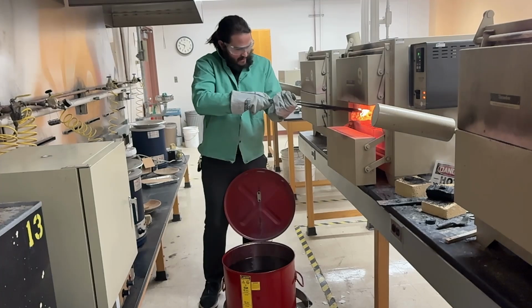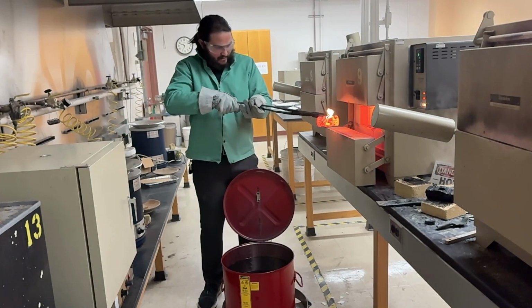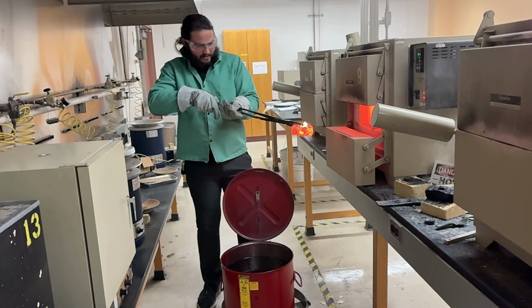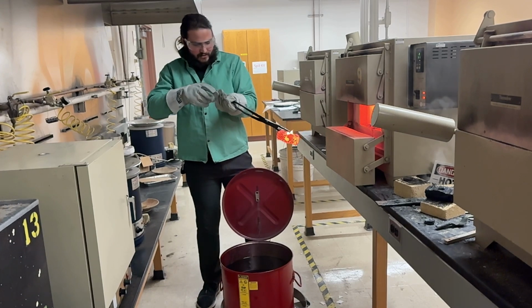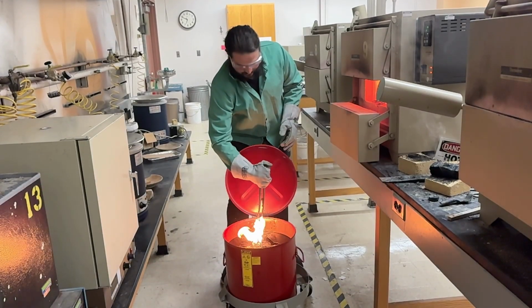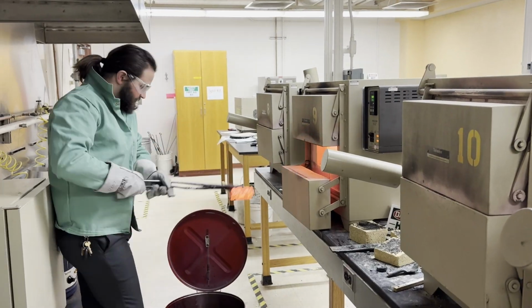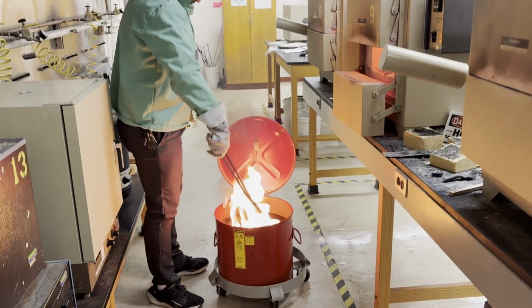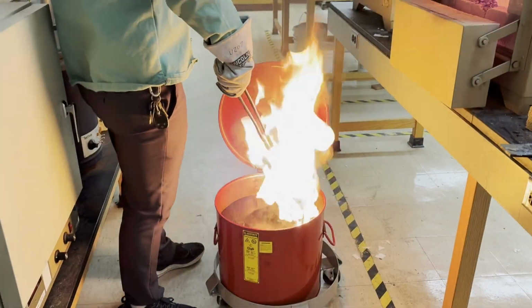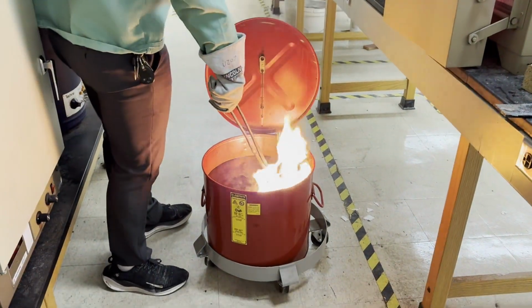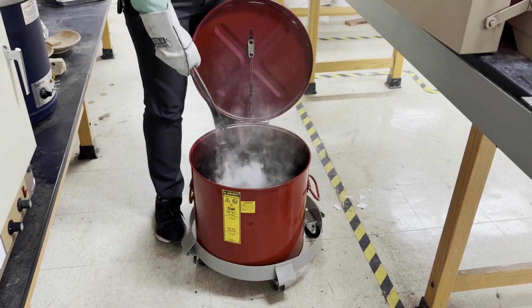So we austenitized at 950, and then we did an oil quench. And after that, we needed to go into a tempering furnace because we get this thin shell of martensite, which is really hard, but it's also kind of brittle. So after we quenched it, we went into the tempering furnace. That was initially at about 250 degrees C for an hour, and that just kind of broke up the martensitic phase, and it's still really hard. We still have really fine-grained material, but now it won't crack.